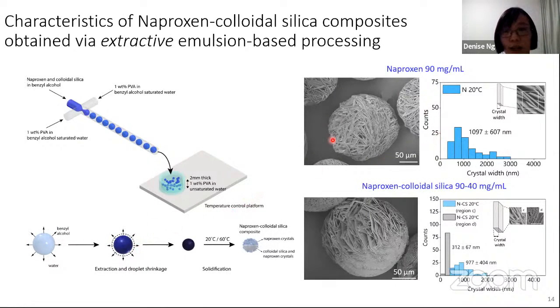In the case of neat particles, we observe that it forms spherical particles with large lath-like crystals, and the crystal widths likewise are approximately 1 micron in size. Whereas what's interesting is that in the case of our colloidal silica composites, it forms a colloid-poor region where large lath-like crystals, approximately 1 micrometer in crystal width, are formed. And in the colloid-rich region, we actually observe a significant narrowing and a narrower distribution of crystal widths, as well as smaller crystal width sizes.